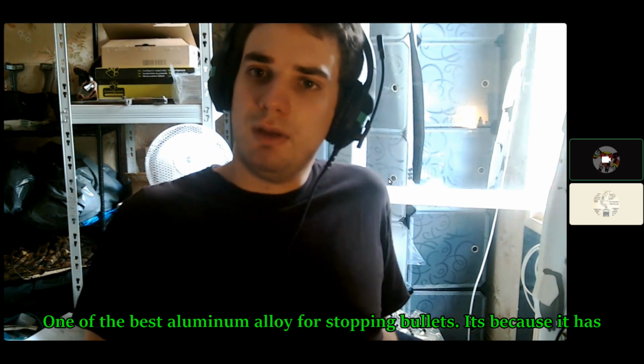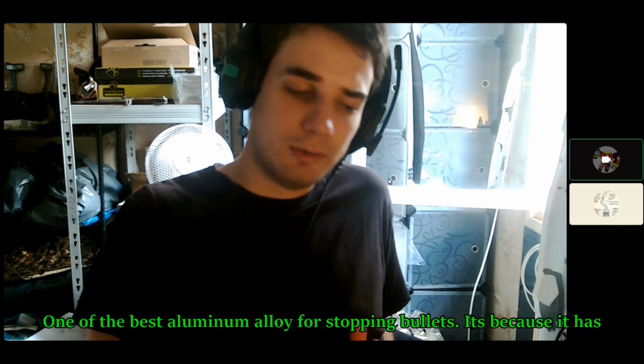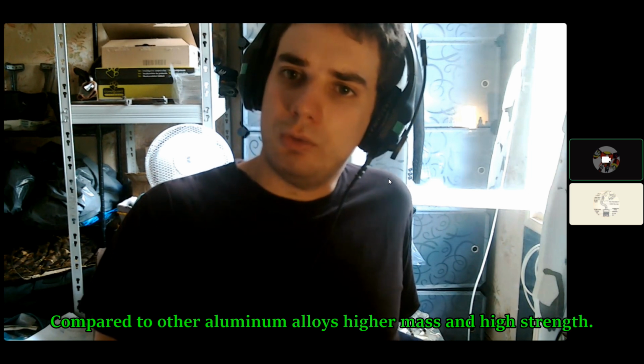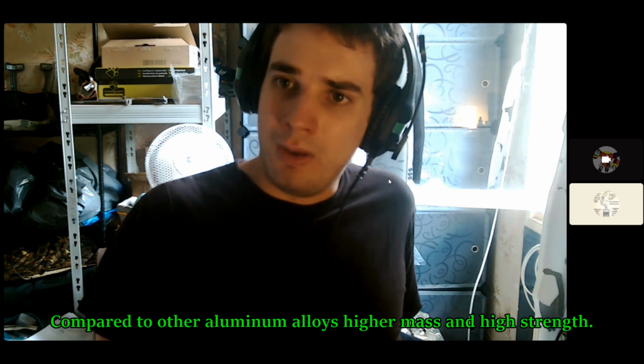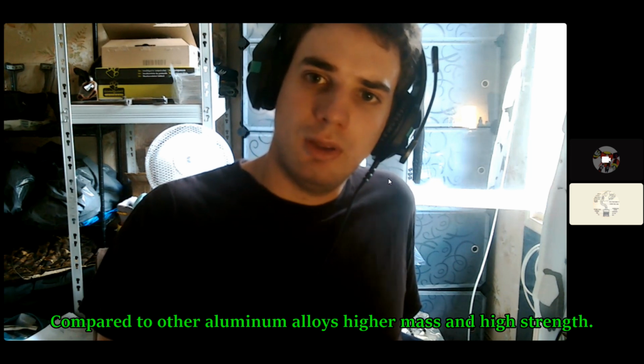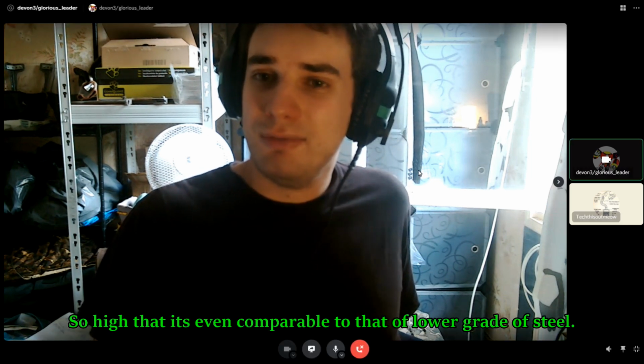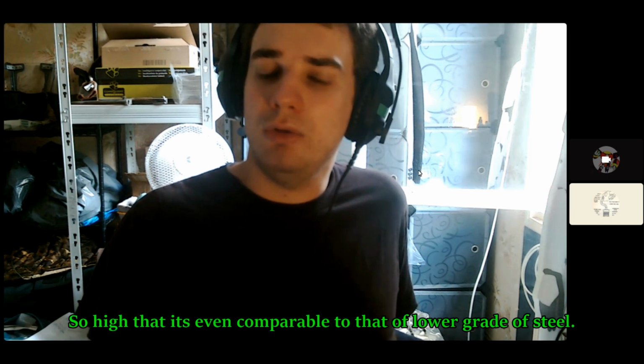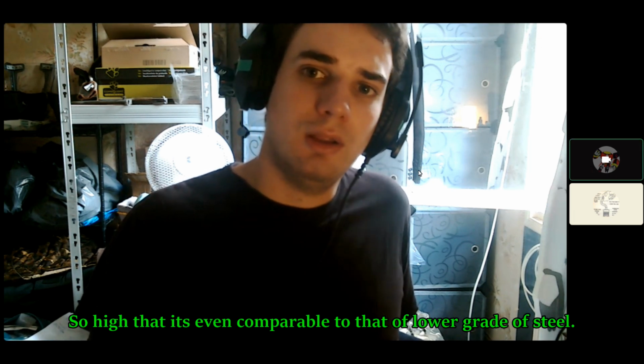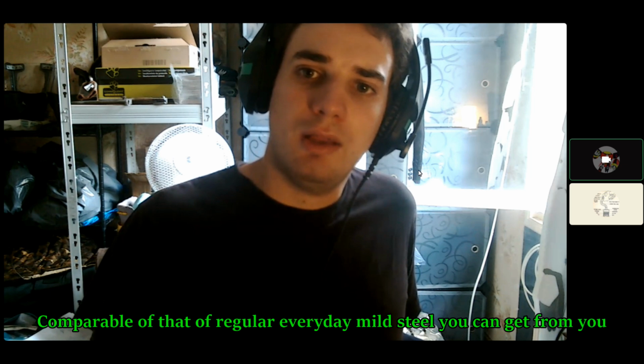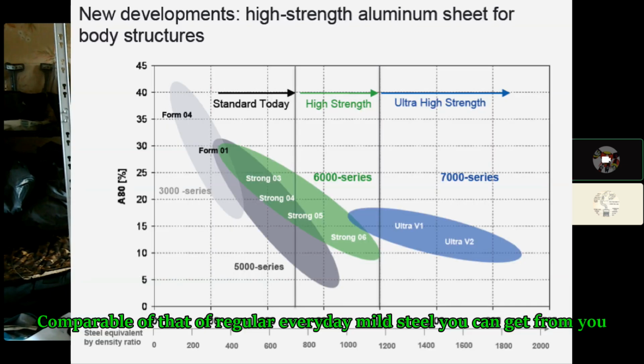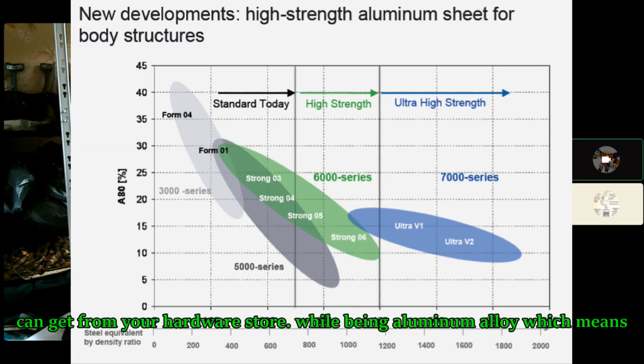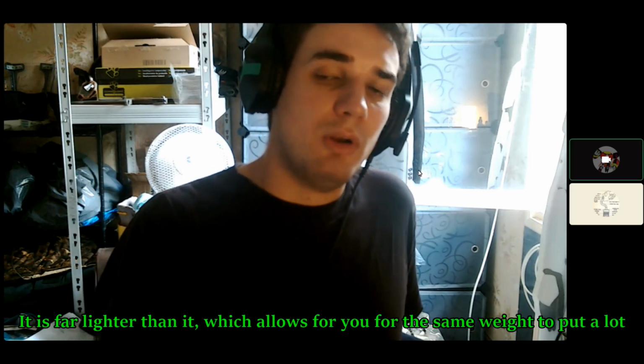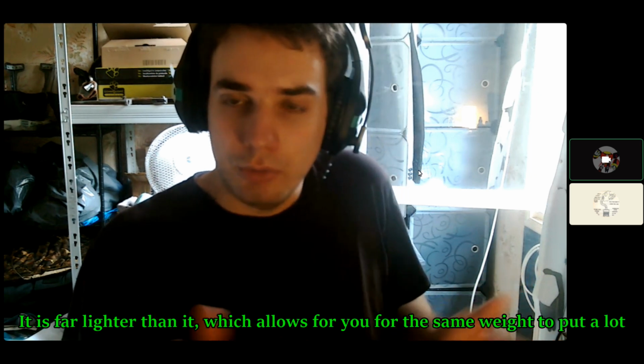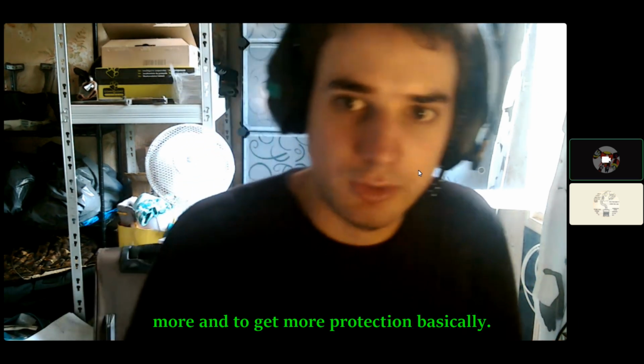one of the best aluminum alloys for stopping bullets. It's because it has, compared to other aluminum alloys, high hardness and a high strength that are so high that they even are comparable to the lower grades of steel. They're comparable to that of the regular everyday mild steel you can get from your hardware stores, while being an aluminum alloy, which means it is far lighter than it, which allows you for the same weight to put a lot more and to get more protection basically.